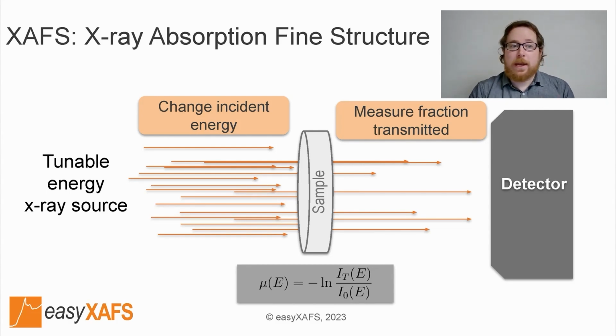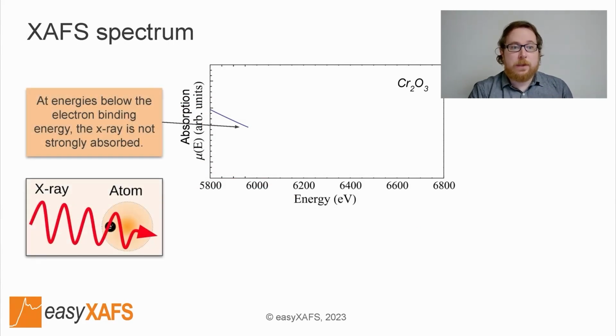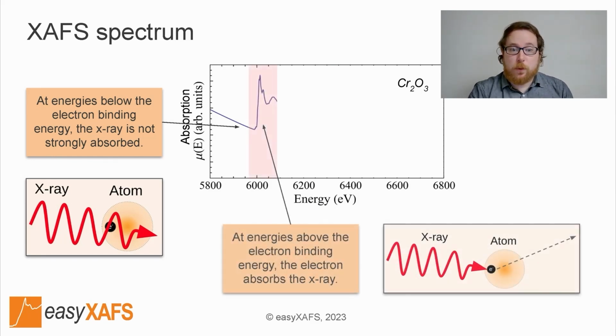So let's take a look at what an actual XAS spectrum looks like. Starting here below the binding energy, absorption will tail off smoothly as high energy X-rays are more penetrative, right? So more penetration, less absorption. And this continues smoothly until you get to regions near and above the binding energy. Here, additional absorption turns on as the X-rays can be absorbed by a core electron, first transitioning to unoccupied atomic states before then becoming an unbound photoelectron once the binding energy has been exceeded.